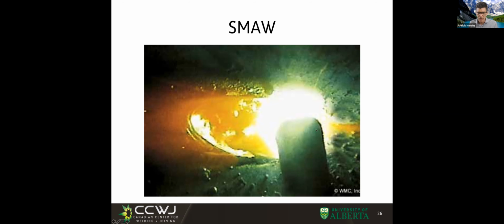What we see here is the electrode, and actually what we see on the surface is the flux cover of the electrode. That's why they call it shielded metal arc welding. The shielded is all these fluxes around the electrode. It's outside. Remember, in flux core, it was a tube with the fluxes inside. Now the fluxes are outside. Here we have the arc.